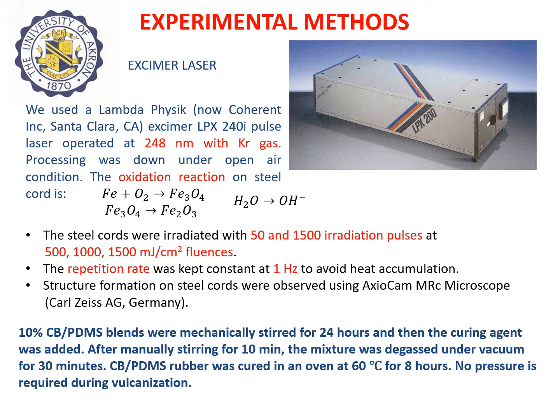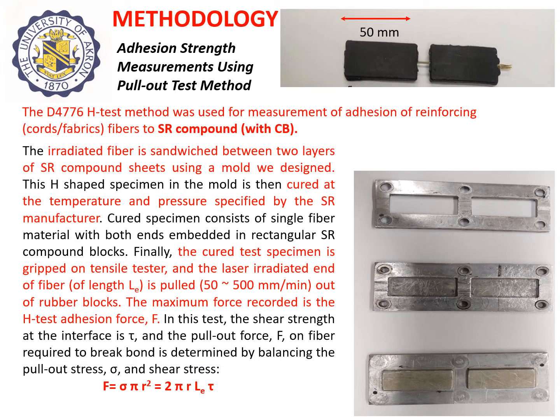The 10% carbon black PDMS blends were mechanically stirred for 24 hours, and then the curing agent was added. After manually stirring for 10 minutes, the mixture was degassed under vacuum for 30 minutes. The carbon black PDMS rubber was cured in an oven at 60 degrees for 8 hours, with no pressure.